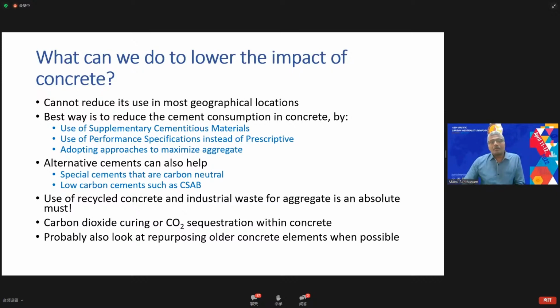So while we cannot reduce the amount of concrete, we can definitely reduce the cement used in it, by using supplementary cementitious materials. Typically these are byproducts from other industries, with properties complementary to Portland cement and concrete. Very often, shifting to a performance-related specification for construction projects can help save quite a bit of cement and reduce the environmental footprint of concrete significantly.